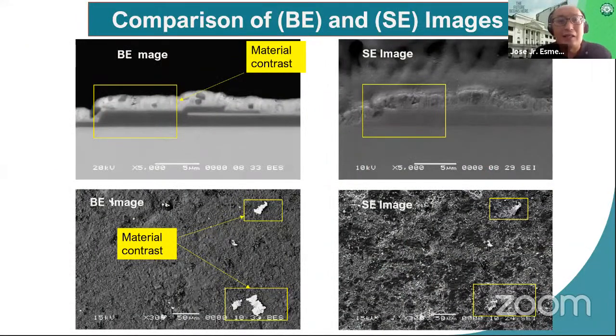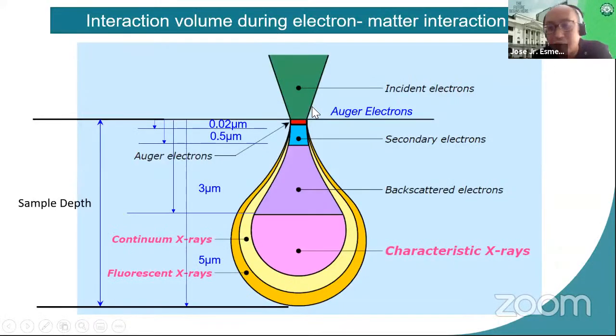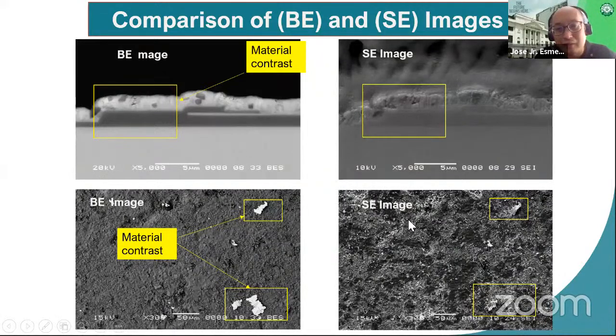Now, this is the difference between the backscatter image and the secondary image. In the secondary image, you can see a lot of these scratches, the features on the surface. But in the backscatter image, you don't normally see these scratches anymore, but you can see the dark portions more visible, and there are a lot of dark elements. It has lower reflectivity. It just tells you that this material has a lower atomic number compared to the white contrast, which has a higher atomic number.